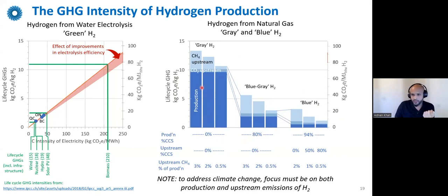Stoichiometrically speaking, when you make hydrogen from natural gas reforming, you make about 9 kg of CO2 for every kg of hydrogen, right? If you add upstream methane emissions, depending on the methane leakage rates you might assume, you can have a carbon intensity of hydrogen anywhere between 10 to 13 kg of CO2 per kg of hydrogen. If you couple that with CCS, you can really drop down the carbon intensity of blue hydrogen, but again, it is very sensitive to upstream methane emissions. So the key message again here is we must address climate change. Therefore, we must focus not only on the technology for carbon capture and storage, but we must also address the upstream emissions from methane extraction and transport to your facility for making hydrogen.